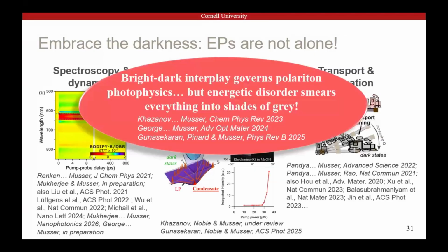And it gets even worse because the states aren't just dark. As soon as you look at real materials, they're not these perfectly well-defined exciton energies that define that model on the previous slide. They are broad disordered potatoes. And as soon as you have disorder, this idea of bright and dark states starts to fall apart, and everything becomes a little bit gray. There's a smattering of photon character in every state, and the brighter states aren't quite as bright as you would expect. So all of this is lurking in the background in everything we think about polaritons.